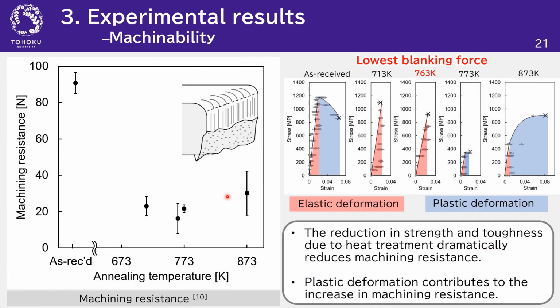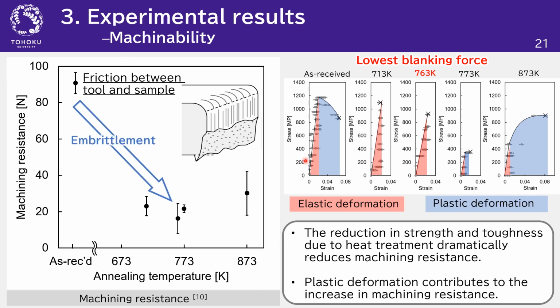The left figure shows the relationship between heat treatment temperature and machining resistance. For the as-received specimens with high strength and toughness, machining resistance was higher due to friction with the tool. By decreasing the strength and toughness through heat treatment, the machining resistance was significantly reduced. On the other hand, the machining resistance increased again when the plastic deformation ability increased. This indicates that the reduction in strength and toughness due to heat treatment dramatically reduced machining resistance, while plastic deformation contributes to the increase in machining resistance.